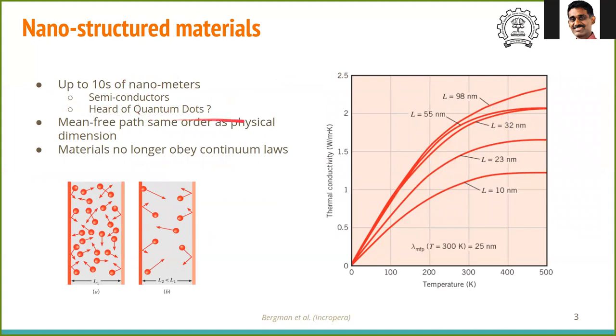When you start reducing the size of silver or any of these materials, the thermal conductivity also changes. This is a typical plot of thermal conductivity versus temperature. For large materials — say a few hundred nanometers, about 98 nanometers — beyond 50 nanometers the thermal conductivity does not change much with temperature. However, keeping the same temperature and reducing size from 100 to 30, 20, and 10 nanometers, the thermal conductivity decreases considerably — in this case by at least about 50 percent. Going smaller and smaller, thermal conductivity reduces even further at a faster rate.